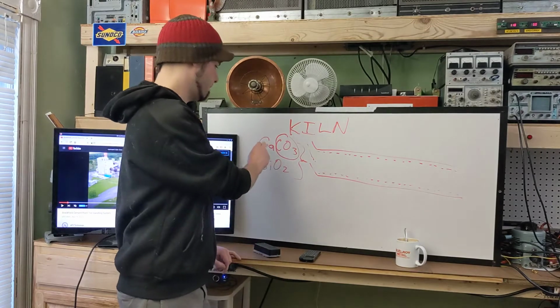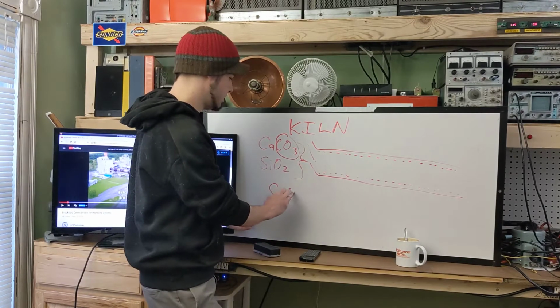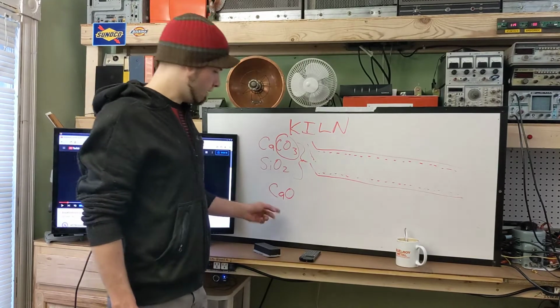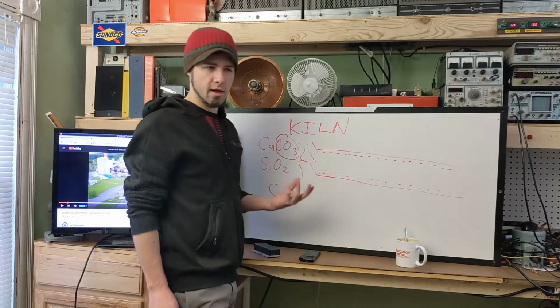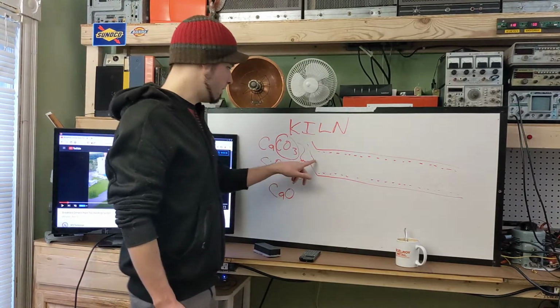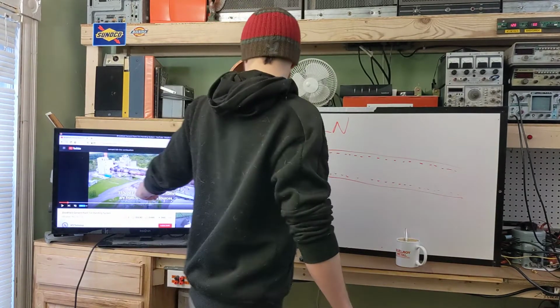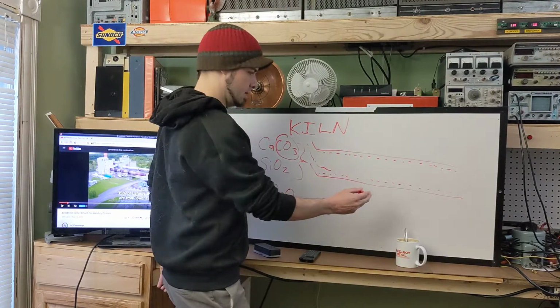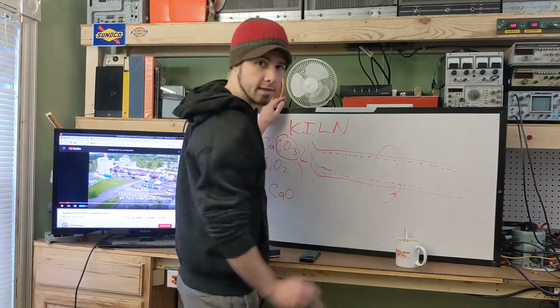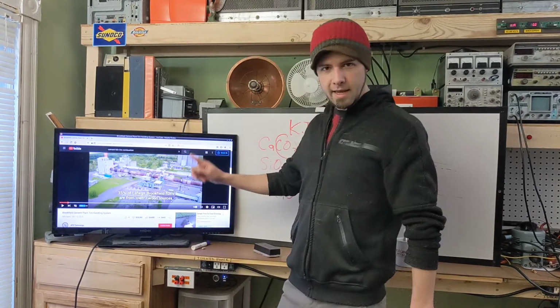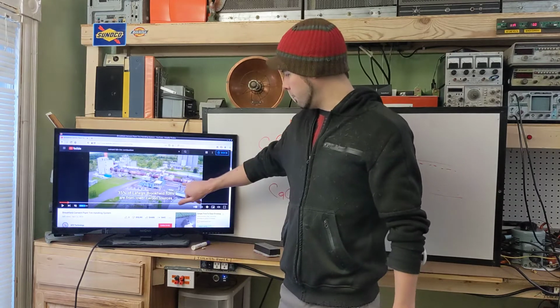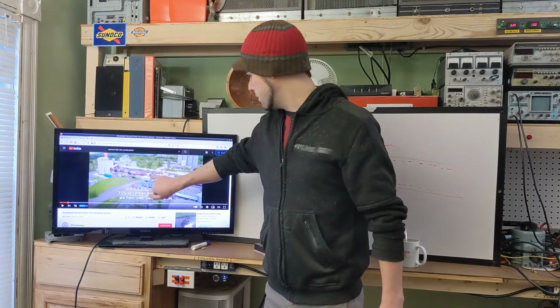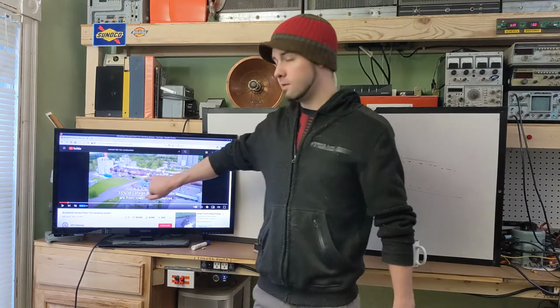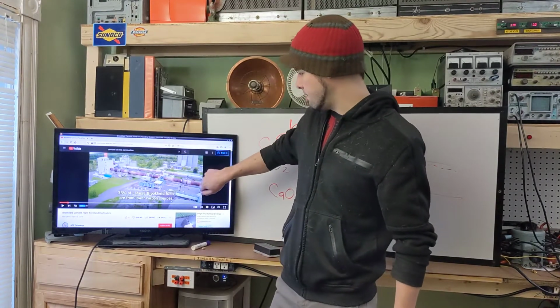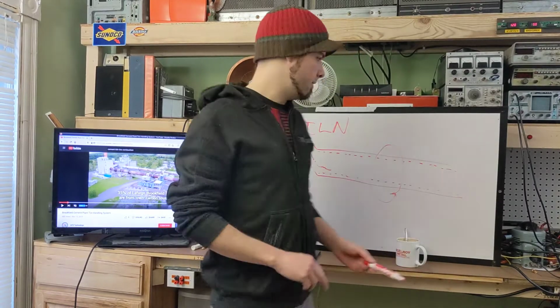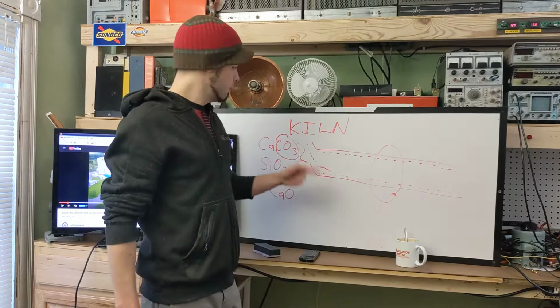So basically you're converting CaCO3 into CaO, which is quicklime. So that's lime, as in quicklime, reactive lime. CaO then enters this long rotary kiln, and it kind of tumbles through here. So this entire kiln rotates axially. So these tubes are actually spinning, and there's rollers. Looks like there's 1, 2, 3, 4 sets of rollers visible in this picture, and it probably even has another set in the back here. And those rollers rotate the kiln, so all the material is tumbled through this.